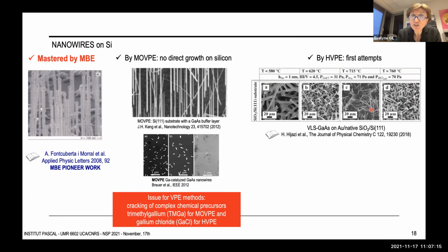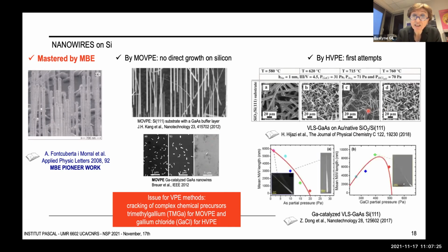Well, these nucleation problems we don't really have in HVPE if we use gold to catalyze VLS growth, here of gallium arsenide nanowires. But nucleation problems, I mean, we do have if we try to implement gallium catalyzed VLS growth. So in the first case, we observe uncontrolled growth with a high density of nanowires, because here growth was carried out on unpatterned native oxide on silicon or bare silicon surface. I don't remember exactly. And in the second case here, a bad preparation of the silicon surface led to very few nanowires due to nucleation issues.